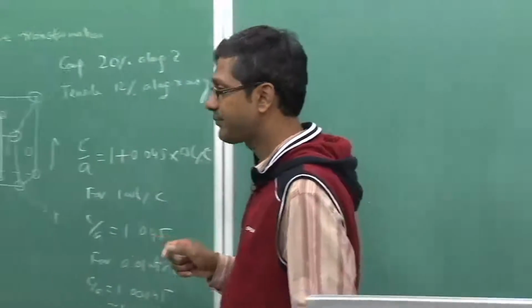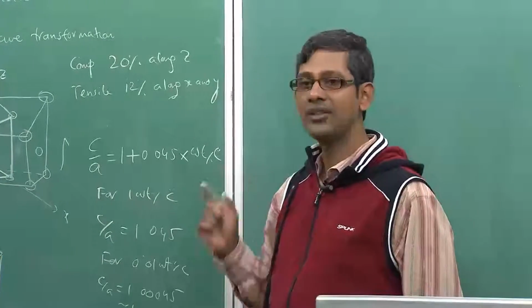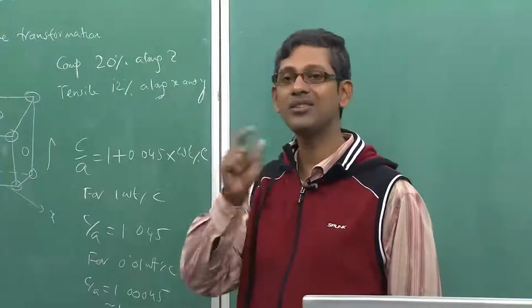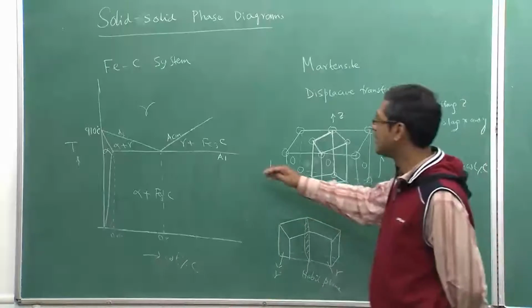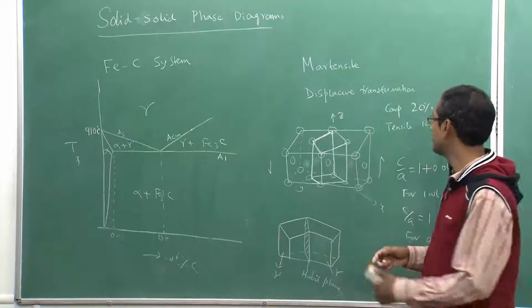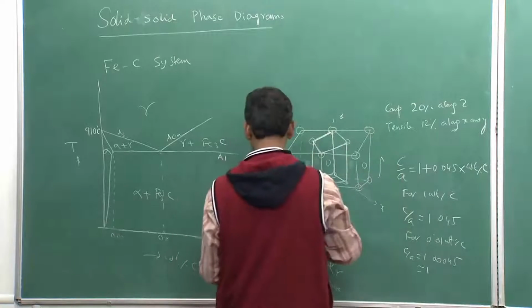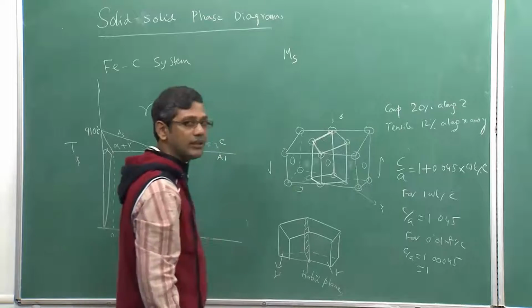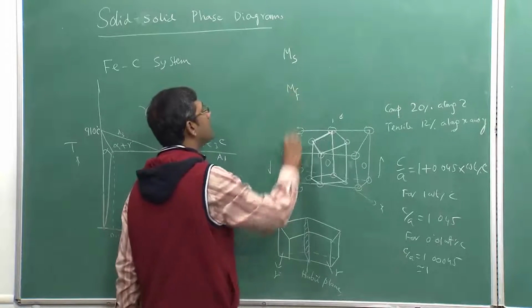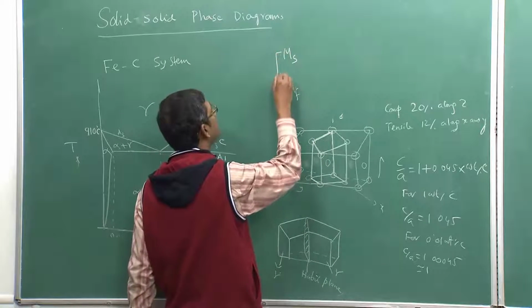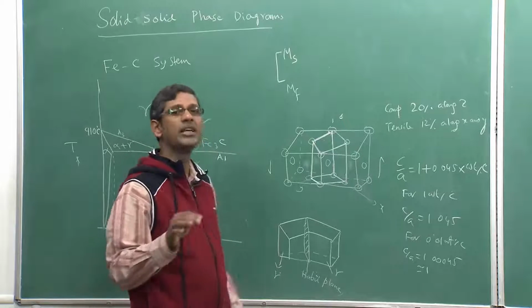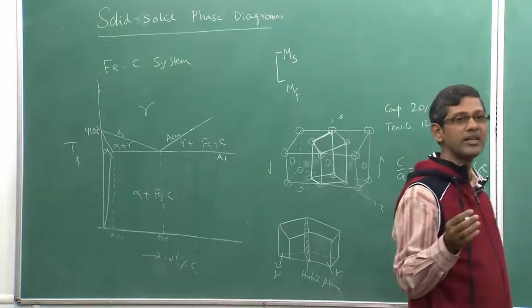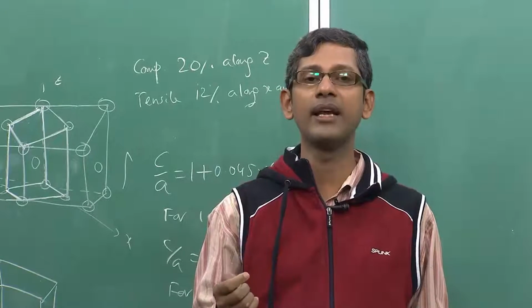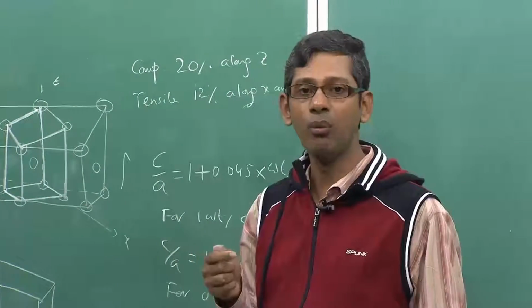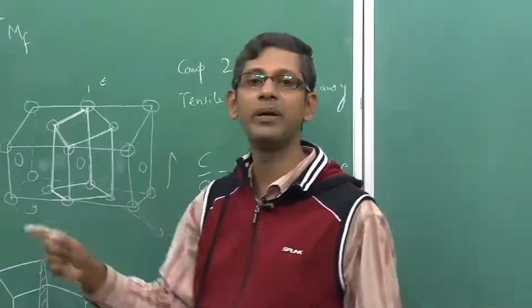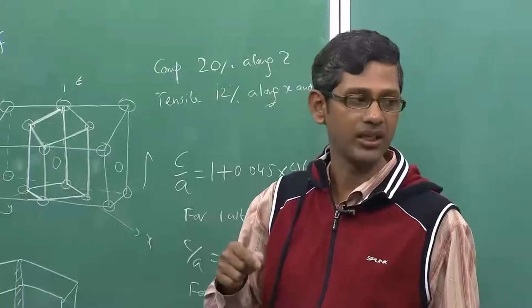Second important thing you must remember is that this transformation starts at a specific temperature for a particular steel. You cannot start at any temperature. Like for pearlite, the transformation starts at any temperature below A1. For martensite, it always starts at a temperature known as the MS temperature. This is what is called the martensite start temperature. That depends on the carbon concentration of the steel, and it ends at a temperature known as MF. So, this is a temperature range in which the martensite transformation happens in steel, and this temperature is very low. For plain carbon steel, MS is about 200 degrees Celsius, and if you add alloying elements, this can go down a little bit. So, in the next class I will give you the formula for the MS temperature, which will depend on the compositions of the different alloying elements in the steel.